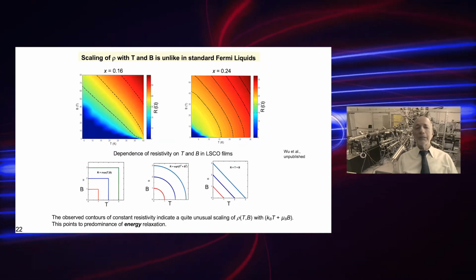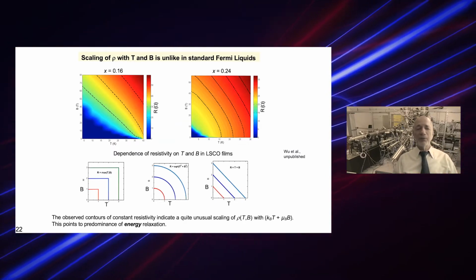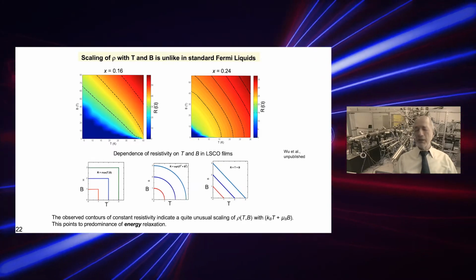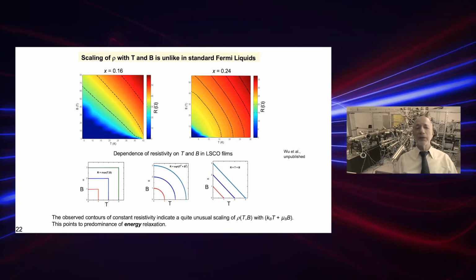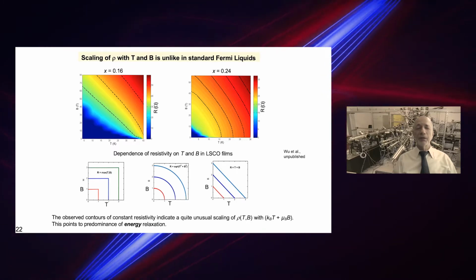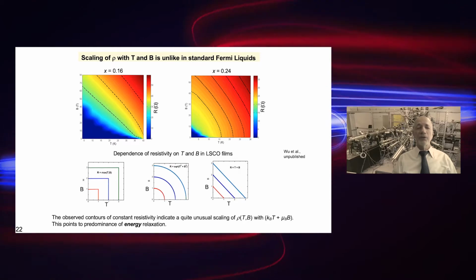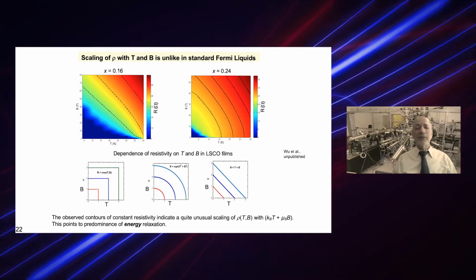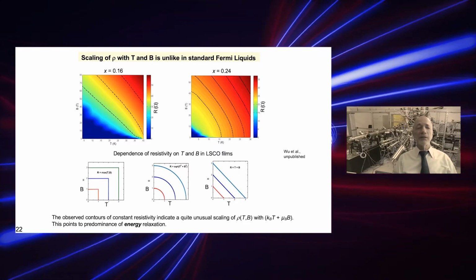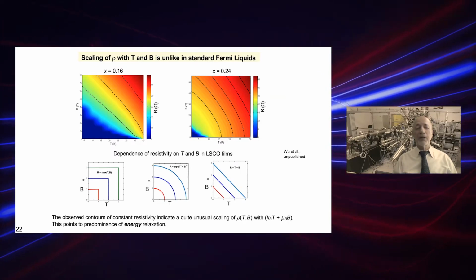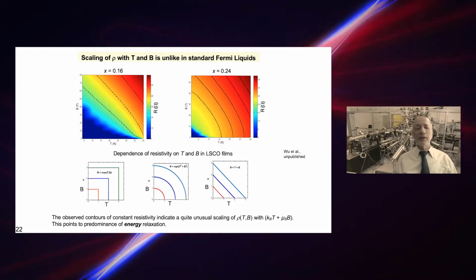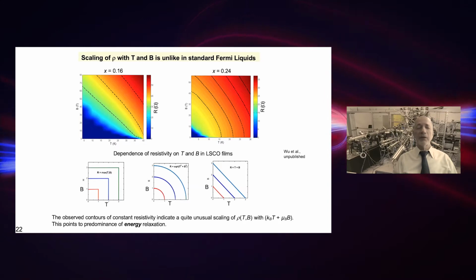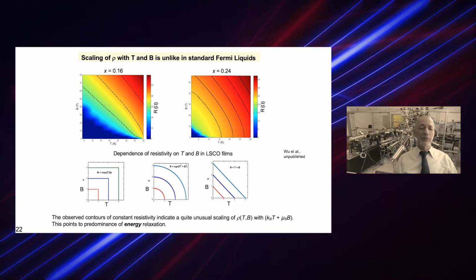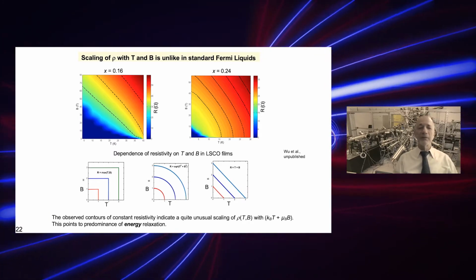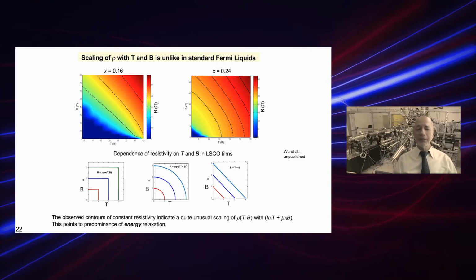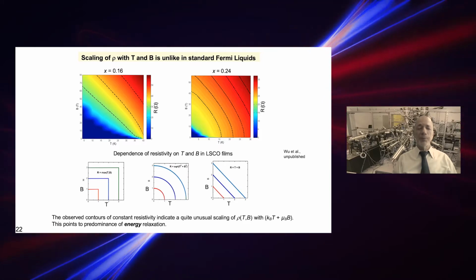Now we could also look at both dependencies at the same time, temperature and field. This I cannot plot in 3D, but what I've done is to color code the measured resistance, and then to guide the eye, I have drawn the curves of constant resistance. So you can see that at optimum doping, these curves are linear except near the axis, meaning for very small field and very small temperature. And this is not what would be expected, not only in Fermi liquid theory, but also in none of the models that have been proposed in the literature.